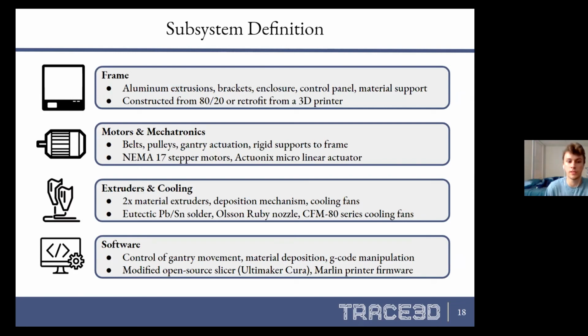The extruders and cooling system will likely be depositing the eutectic tin lead solder alloy, but we are still considering other possible solutions, including lead-free solders as well as some low-temperature materials. We're also tentatively deciding to use the Olsson Ruby nozzle in order to extrude the solder, and we have some choice cooling fans which perform better than those which we use in our hypothetical calculations. Finally, the software we will be using will be a modified form of the open source slicer Ultimaker Cura, and we will be running firmware on our 3D printer of the modified version of the Marlin software.